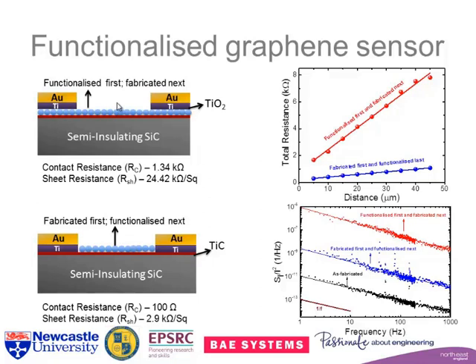As soon as you put photoresist onto graphene, it destroys the surface. And as soon as you destroy the surface, it's very difficult to recover. So in this case, we get a far lower resistance, as what we have here is predominantly a resistive sensor. Having this much lower resistance is going to give us far better sensitivity, and we've got a much lower noise.